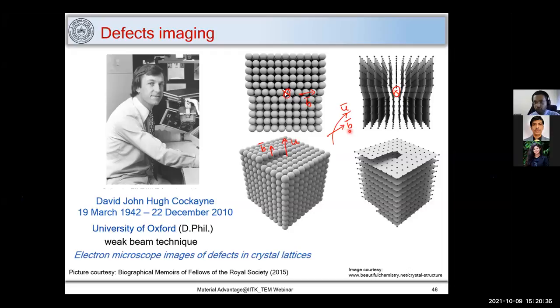Now, a very important point which I'm going to tell you is that this Burgers vector remains invariant. Let me write that down also. Invariant means the Burgers vector doesn't change with respect to the position of this dislocation. For a given dislocation, the magnitude and the direction of the Burgers vector remain the same. So this is a very important one when you try to image dislocations.